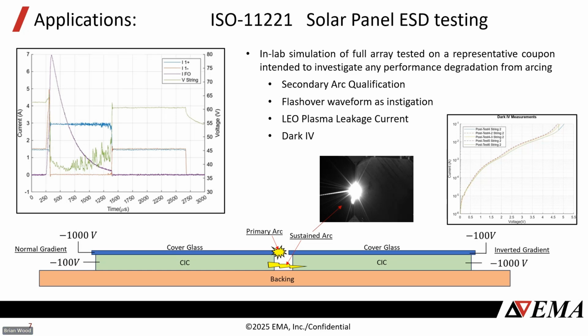And so that's one of the tests that we are comfortable doing here in the SERE lab, where you give us a solar coupon, which is a representative coupon of what you might send up into space, and we load that into the chamber, and we will start to bias the strings to kind of simulate any charging that would occur on the chassis. We expose it to the low energy plasma, and we start inducing these little primary arcs, and then we start to see if any of those are producing any type of sustained arc in between that gap there.